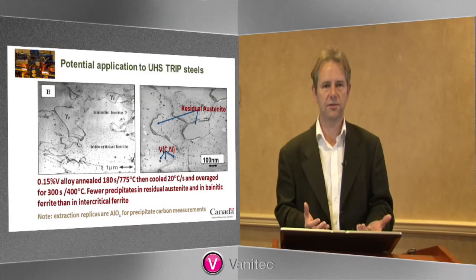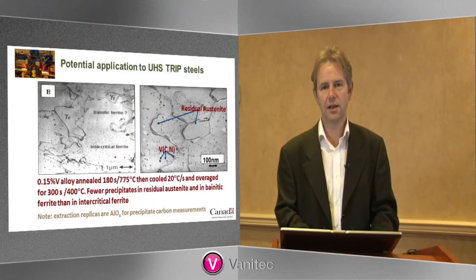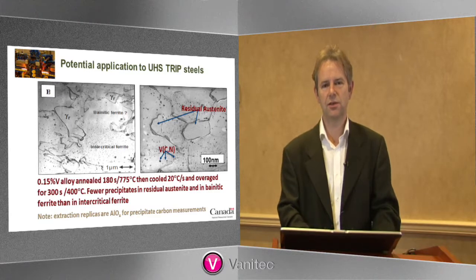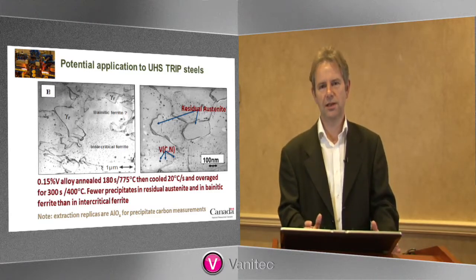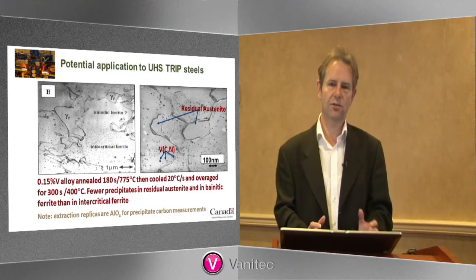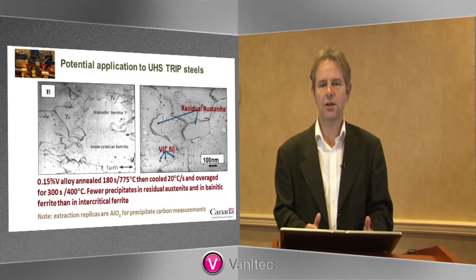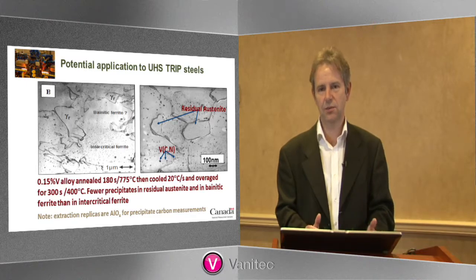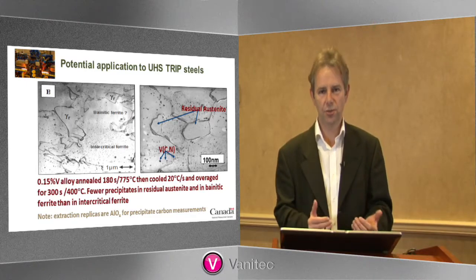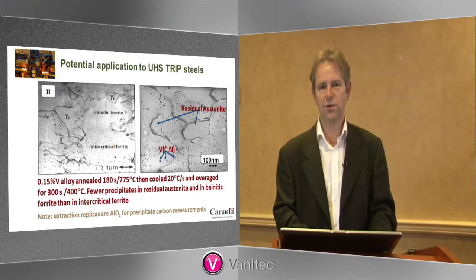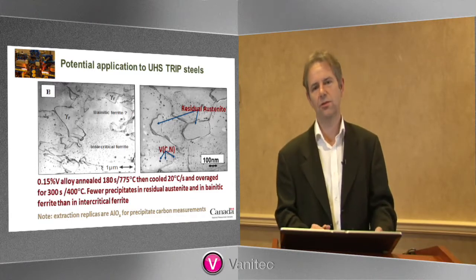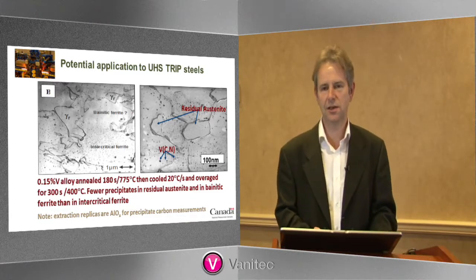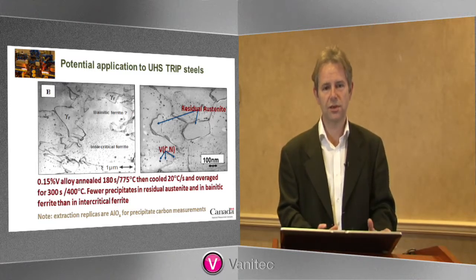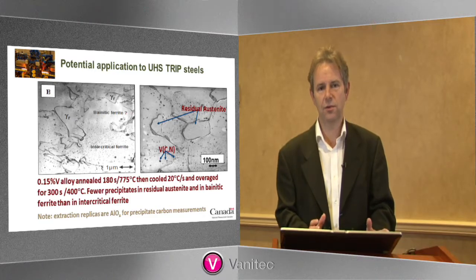So it gives you a selective strengthening of the ferrite phase, and that is something that is extremely interesting, because in these microstructures that's exactly what you want to do. You don't want carbides precipitating in residual austenite, because that is just going to use up valuable carbon that should be in solid solution, stabilizing that austenite to give you a good TRIP effect. You don't really want to precipitate in the bainite either, because it's not going to give you a very big increase in strength. The phase to strengthen is actually the ferrite phase. That's the softest phase, so it's the most interesting one. So this is exactly what we want to do.